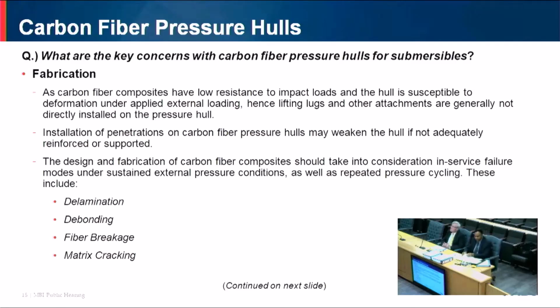So when you design your carbon fiber pressure hull, you also need to consider various failure modes, including delamination, debonding, fiber breakage, and matrix cracking, okay? Delamination basically means separation of the carbon fiber plies. The plies start separating. Debonding means the carbon fiber strands start coming out from the epoxy matrix, okay? Debonding is caused by failure of adhesion between the strands and the epoxy matrix. Matrix cracking is characterized by cracks in the epoxy matrix, and this occurs due to fatigue of the material. Fiber breakage occurs when the carbon fiber strands snap or break, okay? This can be caused by high stresses, by impact loads, or due to manufacturing defects in the carbon fiber. Now, since the carbon fiber strands are the main load-bearing member in the composite, if you have strands that break off, then the strength of the hull will deteriorate and you can have premature collapse of the pressure hull, okay?